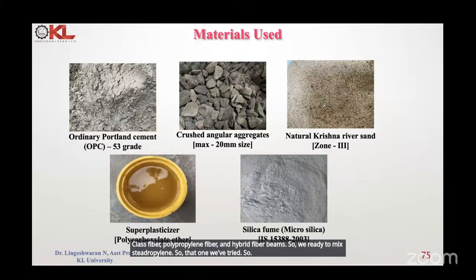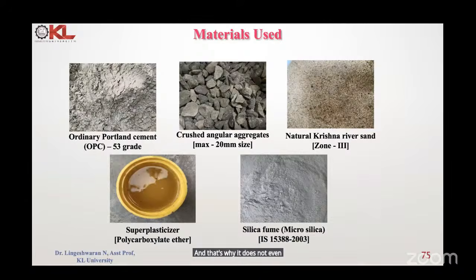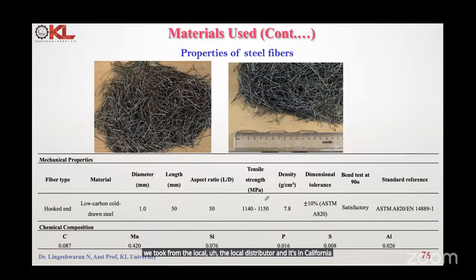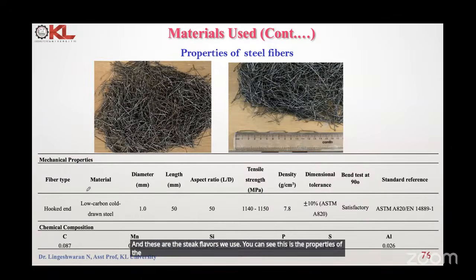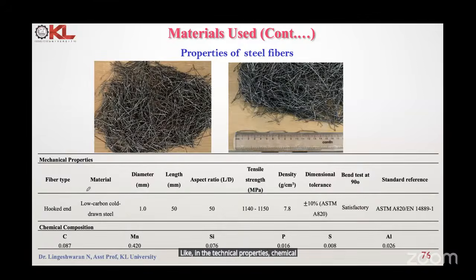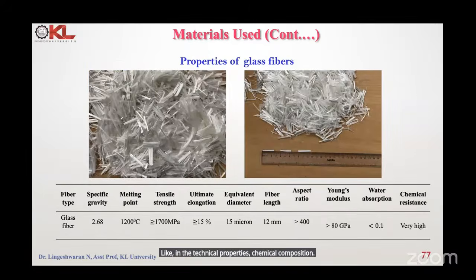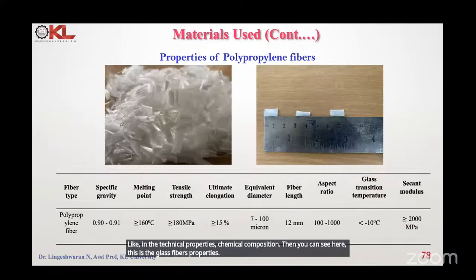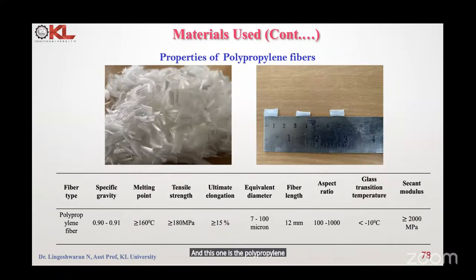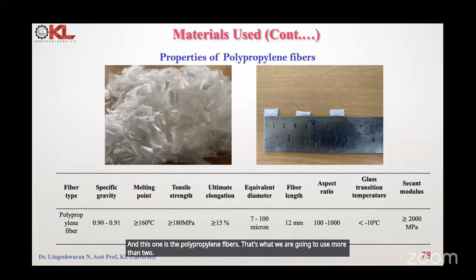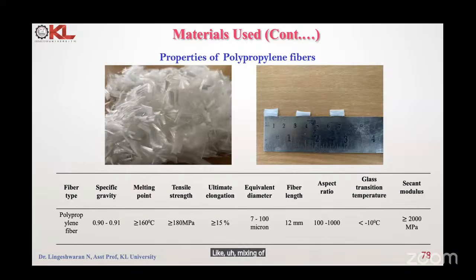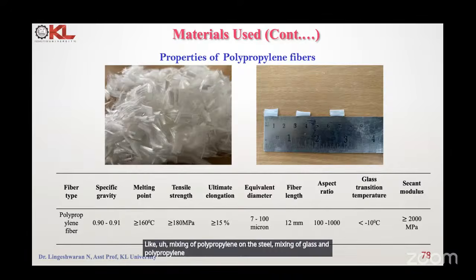So you can see here, these are the materials we used: OPC, 20 mm size aggregate, natural Krishna River sand, and superplasticizer we took from a local distributor, and silica fume, micro silica. And these are the steel fibers we used. You can see the properties of the steel fiber, like mechanical properties and chemical composition. Then the glass fiber properties, and this one is the polypropylene fiber. We are going to use more than two, like mixing polypropylene and steel, mixing glass and polypropylene. That's what we call hybrid fibers.